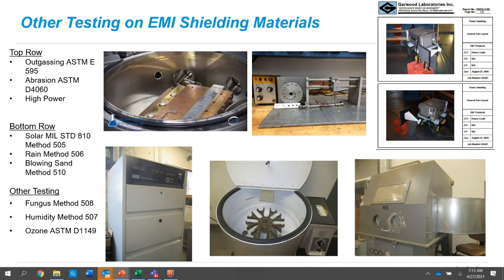And if you know honeycomb, it basically consists of little cells which almost acted as heat pipes. And so even at like 1 watt per square inch, this started getting very, very hot, up to about 400 degrees, and we terminated the test. So certainly airflow is a very big consideration in how these things can handle heat.